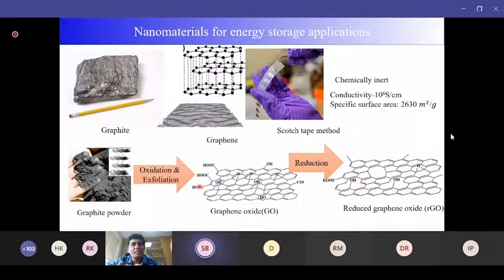These are known as graphene oxide, because it is not graphene, as certain functional groups are attached over the surface. And now by some chemical or thermal reduction method, we can strip off those functional groups to a great extent to get the chemically transformed graphene, also known as reduced graphene oxide. So in this process, we can get kilograms of graphene sample.